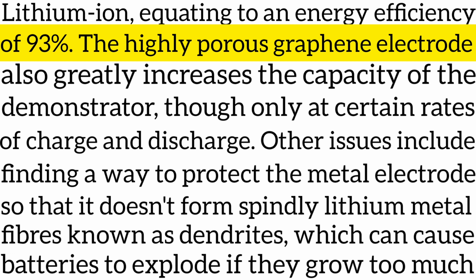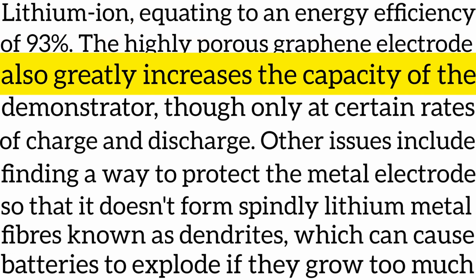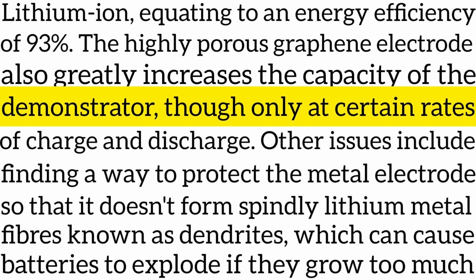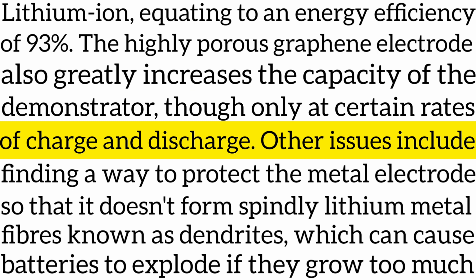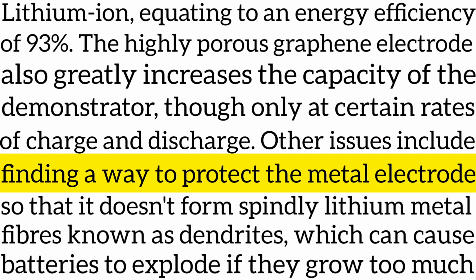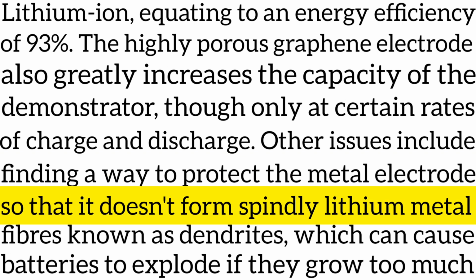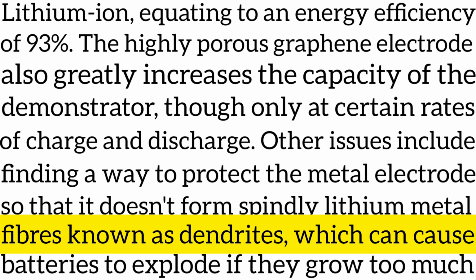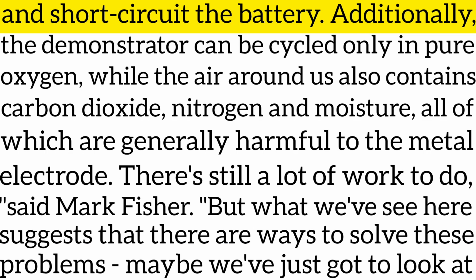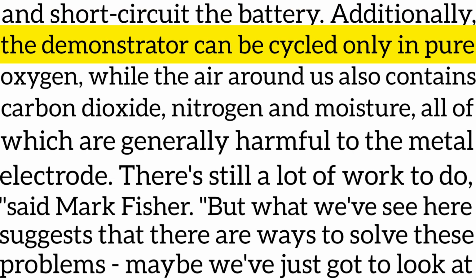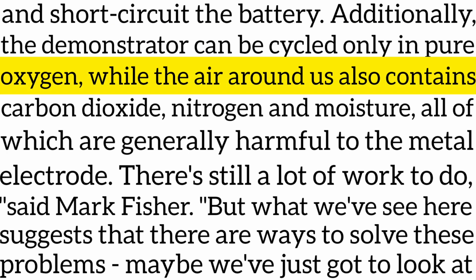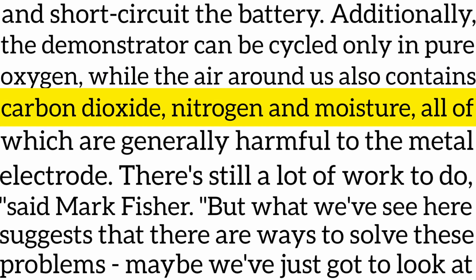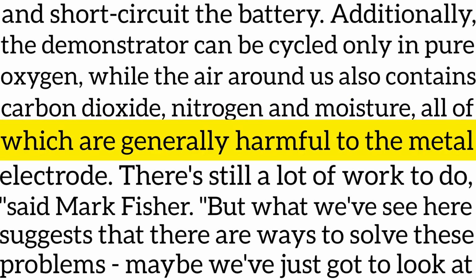The highly porous graphene electrode also greatly increases the capacity of the demonstrator, though only at certain rates of charge and discharge. Other issues include finding a way to protect the metal electrode so that it doesn't form spindly lithium metal fibers known as dendrites, which can cause batteries to explode if they grow too much and short circuit the battery. Additionally, the demonstrator can be cycled only in pure oxygen, while the air around us also contains carbon dioxide, nitrogen, and moisture, all of which are generally harmful to the metal electrode.